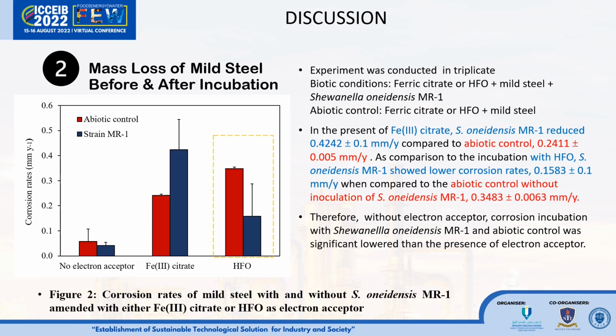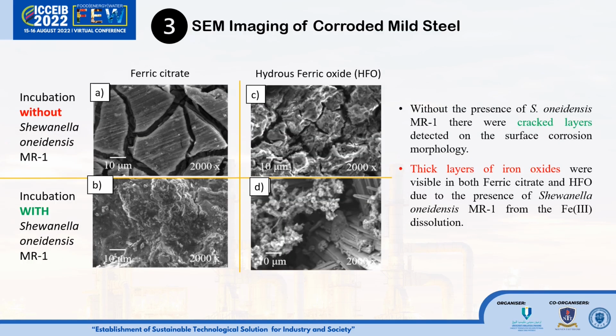This data suggests that Shewanella oneidensis MR-1 was poorly in direct contact with the external ferric oxide due to the higher HFO surface area. The result we obtained from the scanning electron microscopy was much more interesting because, as you can see in the image here, there are noticeable changes in the morphology of corroded mild steel with and without Shewanella. I would like to emphasize picture B, ferric citrate, and D, HFO, inoculated with Shewanella, identified with thick layers of iron oxides formed on corroded mild steel, while absence of Shewanella oneidensis MR-1 in picture A, ferric citrate, and C, HFO, show obvious multiple cracked layers of corrosion morphology on the surface of mild steel.